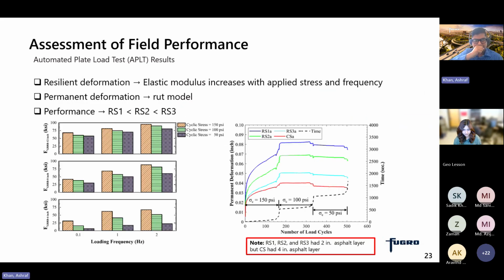Let's look at the results from the APLT. As I said, it can capture both elastic and plastic deformation. So resilient deformation showed that elastic modulus increases with applied stress and frequencies. That means if there is an increase in applied stress, there will be an increase in modulus. And if there is an increase in frequency, there will also be an increase in modulus. That means faster traffic will show a higher modulus. The results show that it has dependency on the frequency of traffic as well.